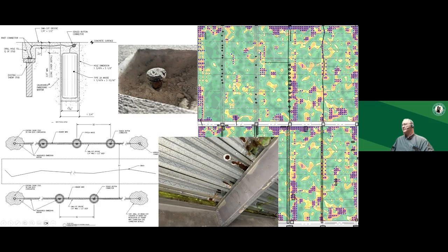And you can see the shear studs over here. And you see them here. These are all ones that had low cover. They had like 1/2 inch of cover. And so the icing salt that was put on there contaminated the surface down to the tops of these. And the top of the head of these would pop the surface off.